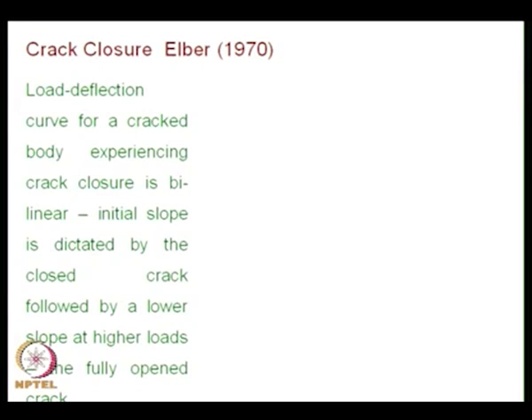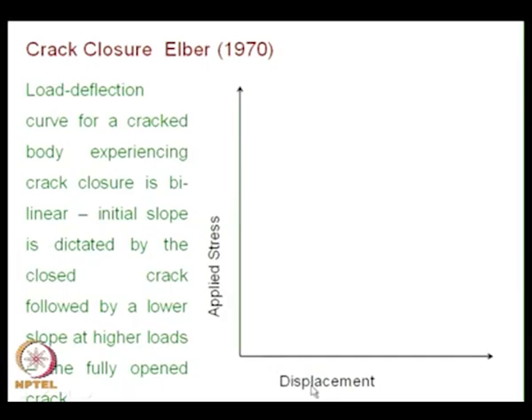So, one of the difficulties is how to see whether the crack is fully opened or not, and how do you judge whether a specimen displays the crack closure phenomenon. People also have methodologies to look at that, and one of the simplest ways is to get the load deflection curve. So, if you get the load deflection curve for a cracked body experiencing crack closure, it is bilinear. This is the observation, and you have the displacement versus applied stress, and the stress displacement relationship is bilinear. So, you have slope changes from the initial to the later part.